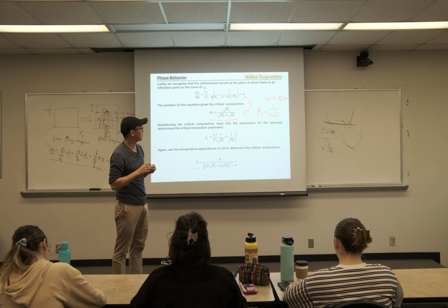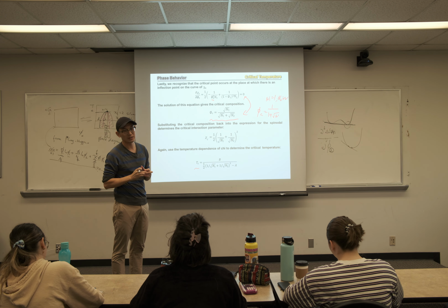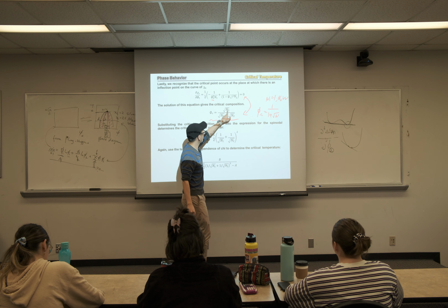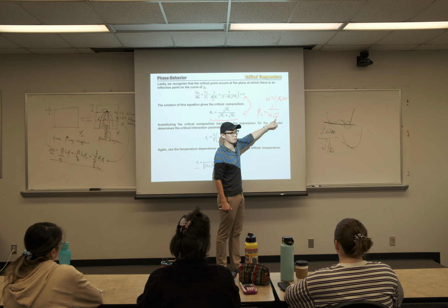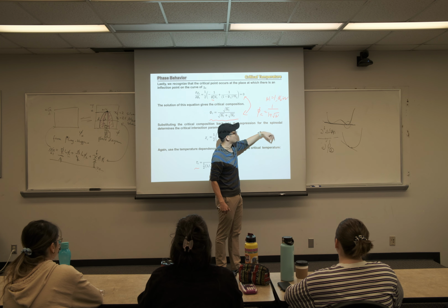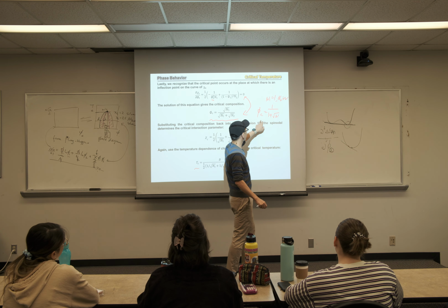But when you start to have polymer in solvent, your phi c will change, and will change a lot. Your N1 is still a small molecule, so you can treat it as 1, and the root of 1 is again 1. But your polymer has a much bigger N, so your phi c is no longer at 0.5. Let's use an example of polymerization N equal to 10,000. If you take the square root, that's about 100. So phi c will be 1 divided by 100, or 1%.